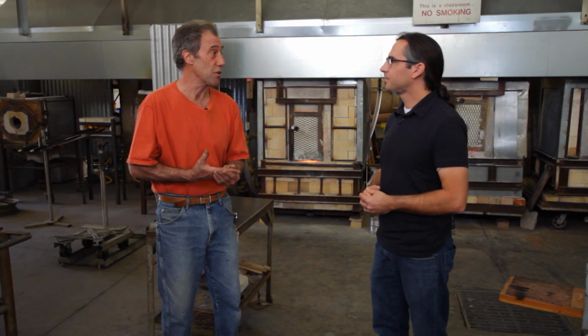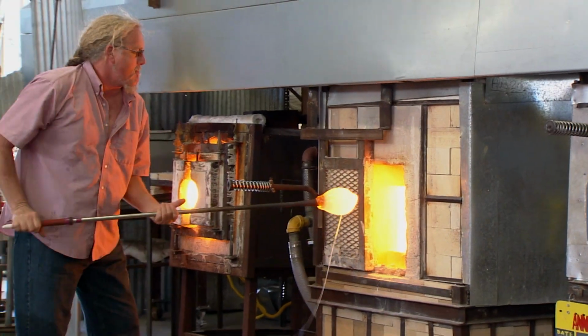What it does there is we know from our experience of using this glass that the annealing temperature is around 900 degrees. So we have our oven set at 900 degrees. And what that does is it relieves all the stress within the glass from the heating and cooling and blowing process, and relaxes the glass enough to make it safe and stabilize the glass. The temperature is then dropped slowly over several hours to room temperature, and then the glass has been annealed.